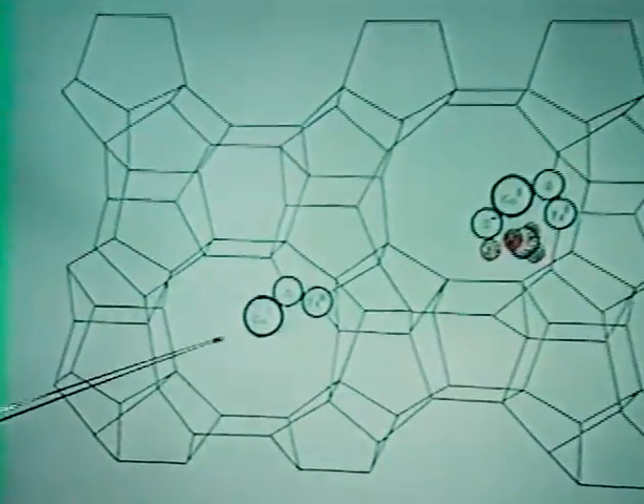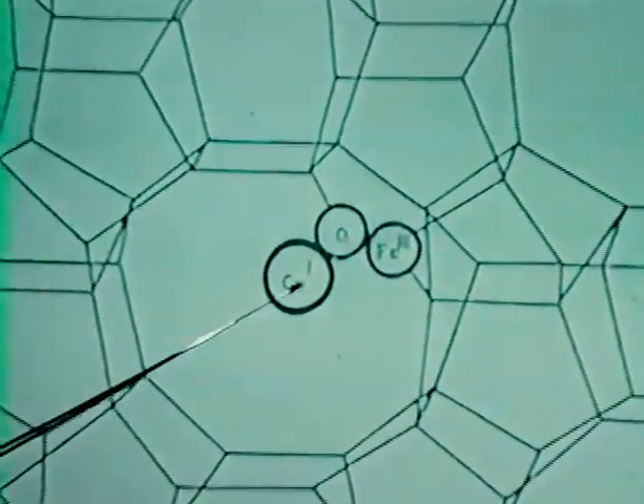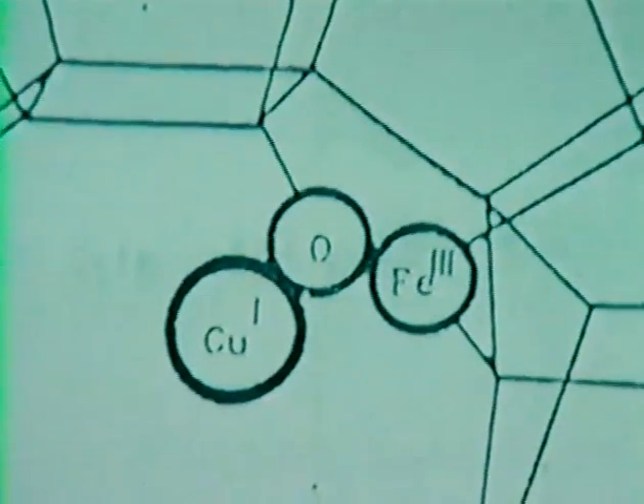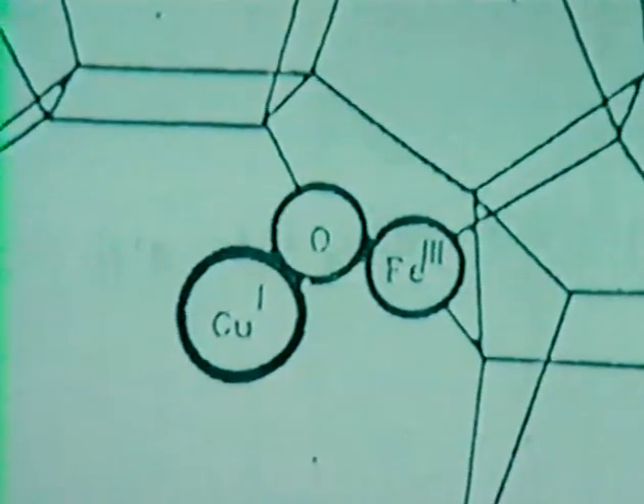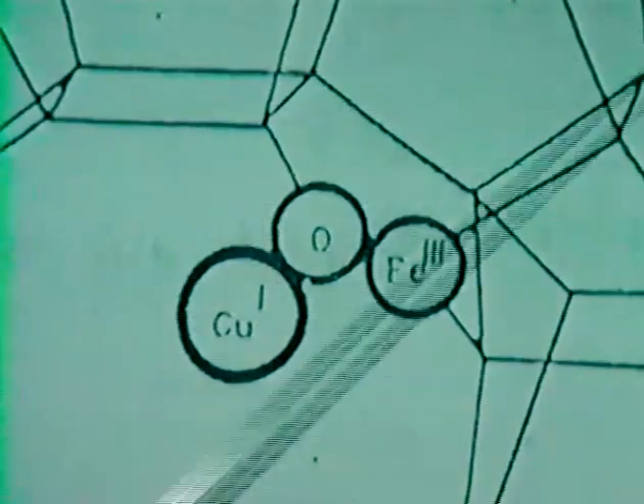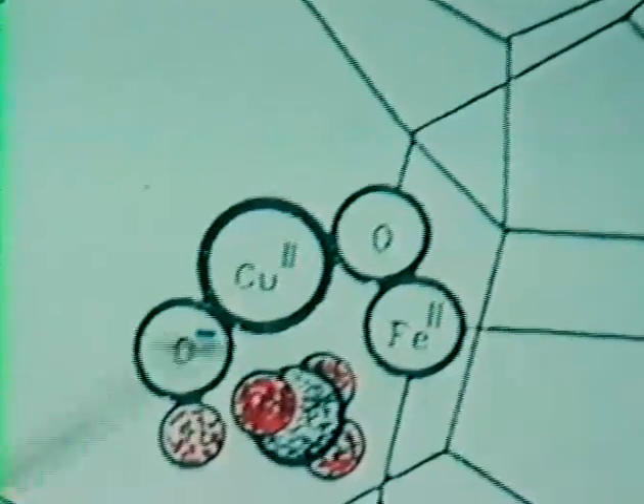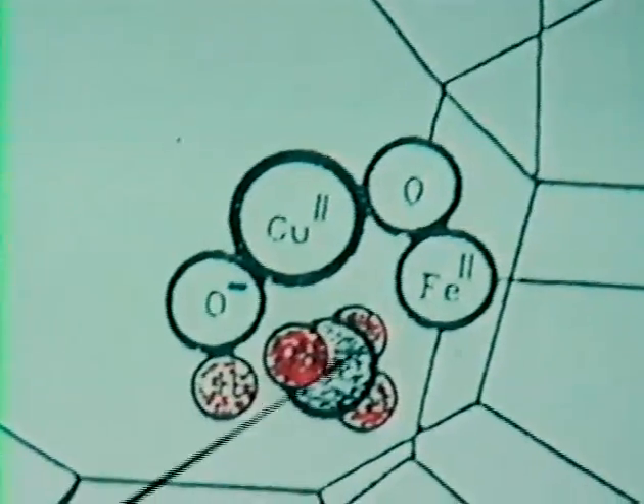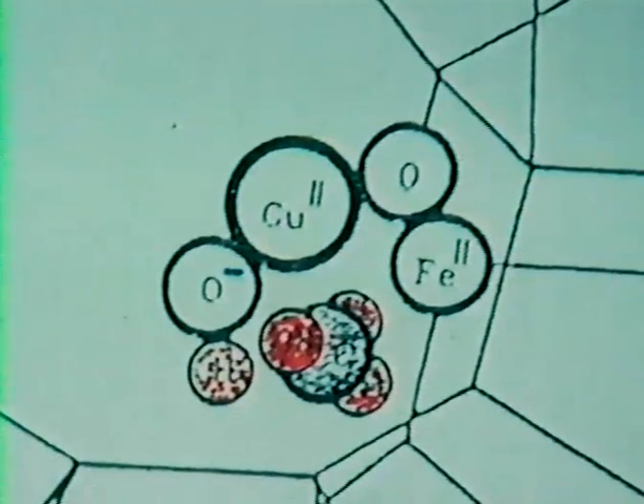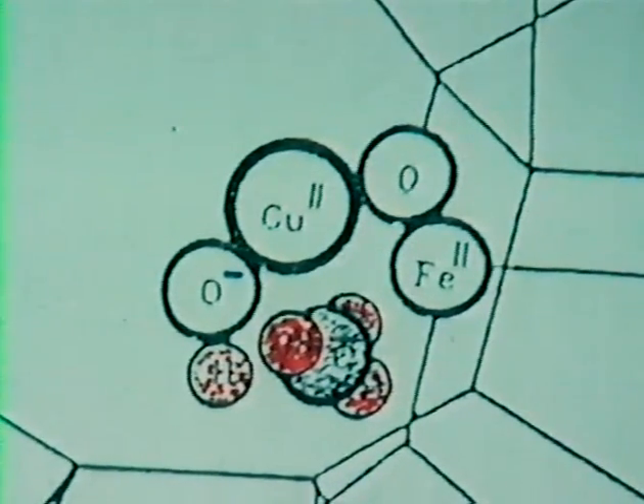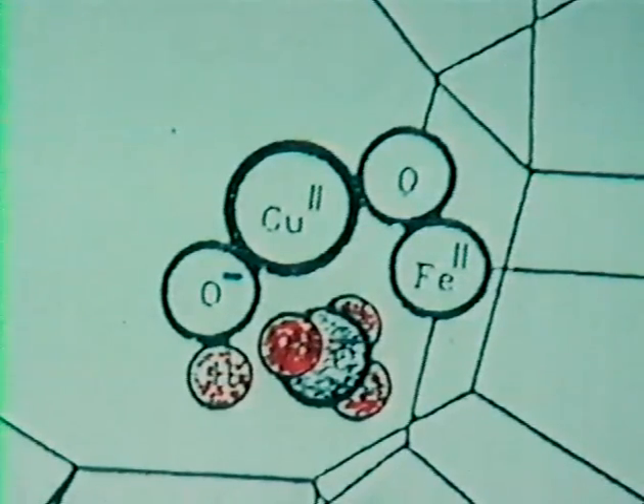Now what you have here is a redox ion, which is going to react with oxygen, and you have a Lewis acid here. So the key to our thinking about activation and conversion of methane, where we did not want to get these methyl free radicals into the gaseous phase, was to have an oxidative attack, but then to have the Lewis acid work on the CH3 radical so that it is converted to something like CH3 carbonium cation. And once that is made, the free radical does not escape into the gaseous phase.